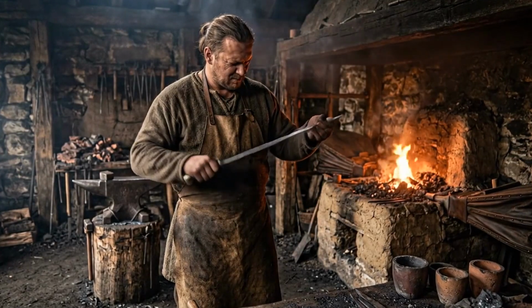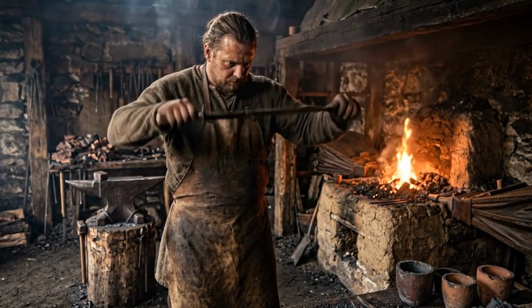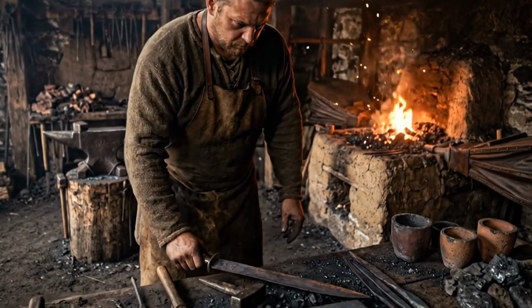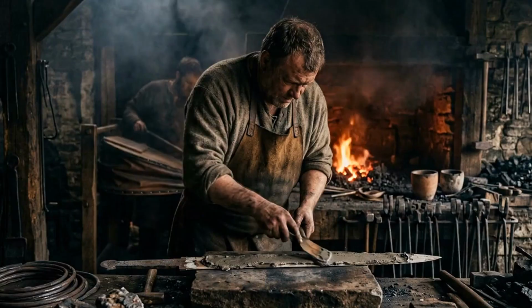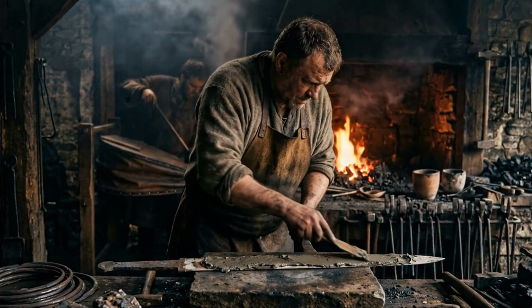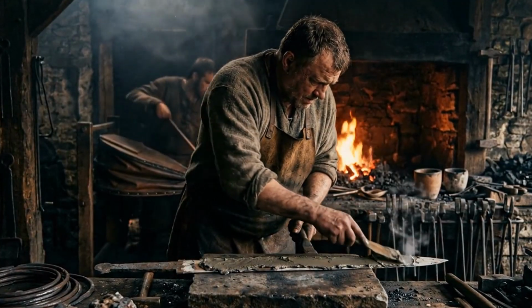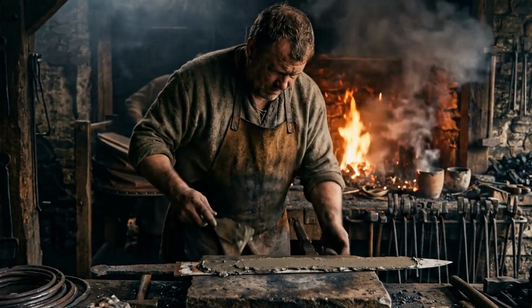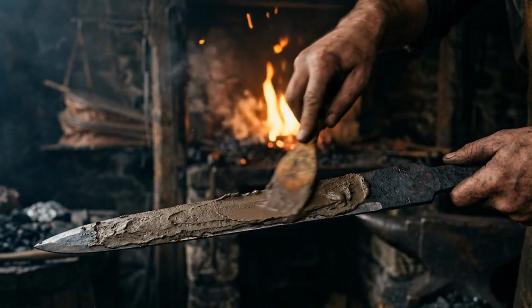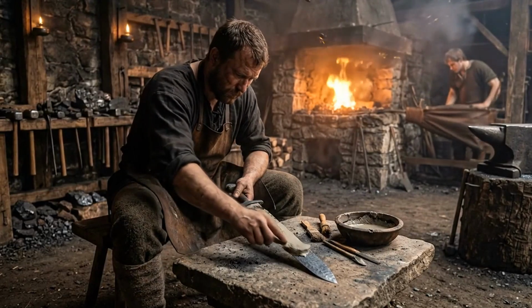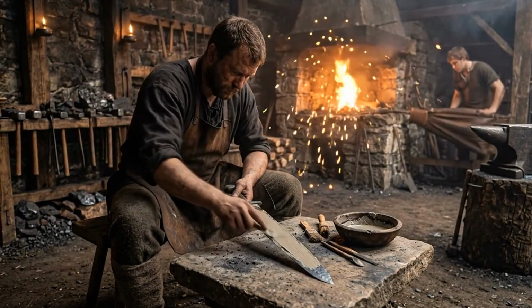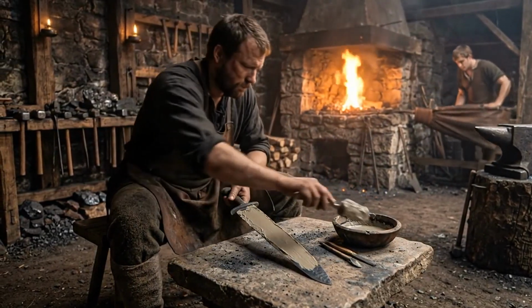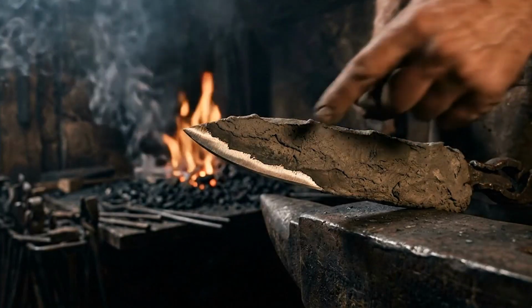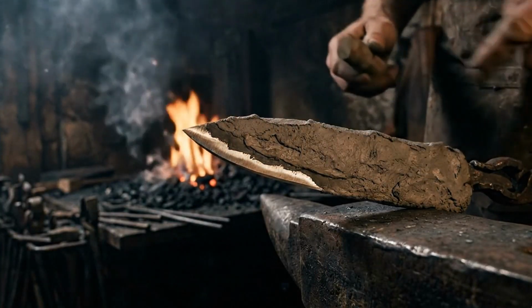The most critical stage of the entire process was the heat treatment, the yaki-ire. Before the blade entered the fire for the final time, the smith applied a clay coating, the tsuchioki, to the surface in a specific pattern. A thick layer of clay was painted over the spine of the blade and the flat faces, while a thin layer or no clay at all was left along the cutting edge.